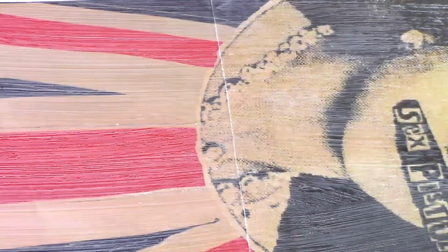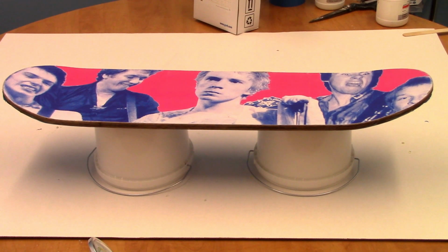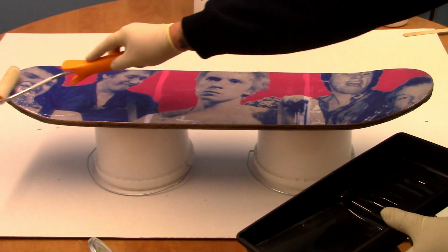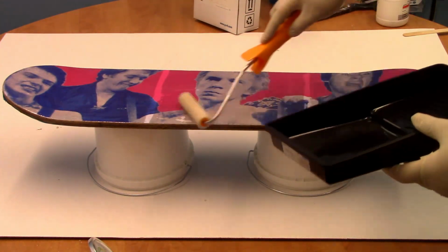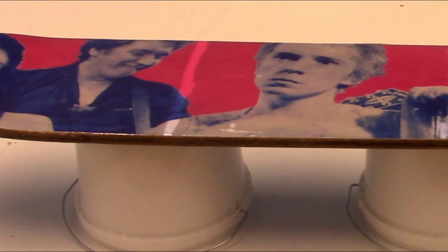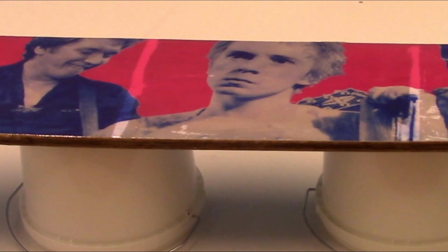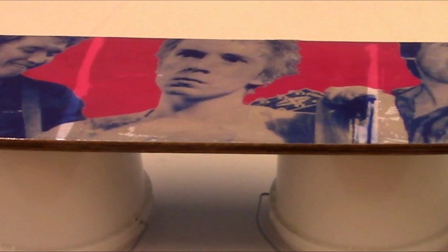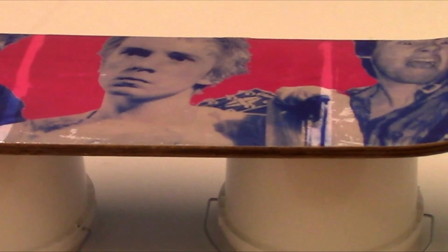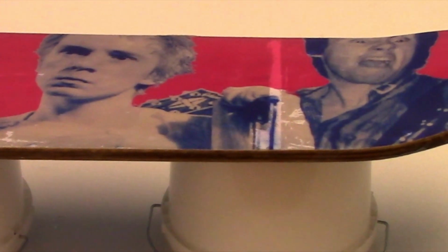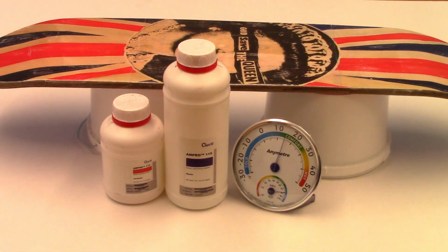It's a good idea to give the graphics another light coat of PVA, which will reduce the paper's porosity and stop the epoxy darkening the image and showing up any glue residues on the seams. We didn't do this on our deck, and as you can see, the glue lines are showing as we wet the area. The imagery remained true to the original printout where there was PVA residue, whereas the rest of the image without any PVA darkened. Once dry, lightly sanded and cleaned, we're ready for our resin coating.